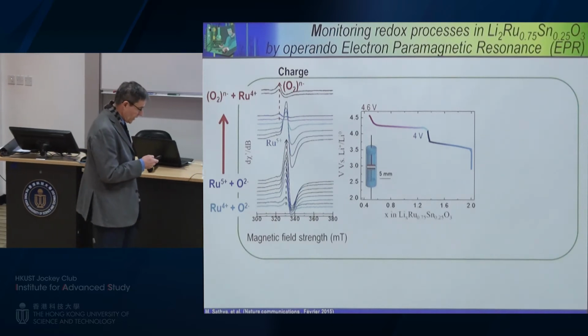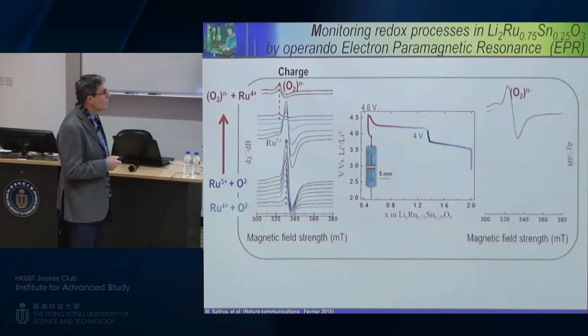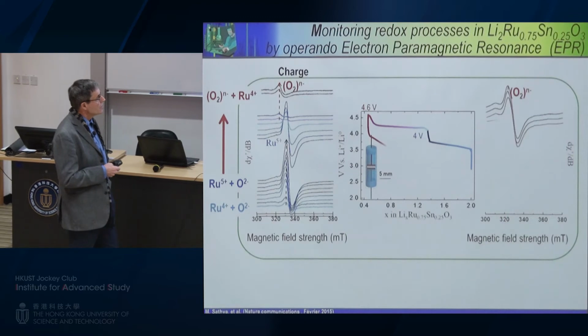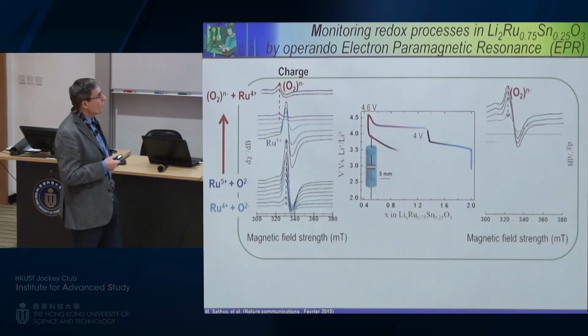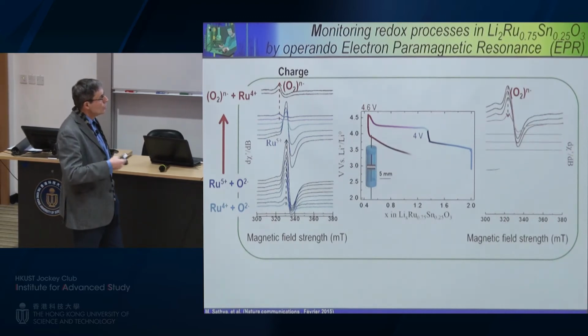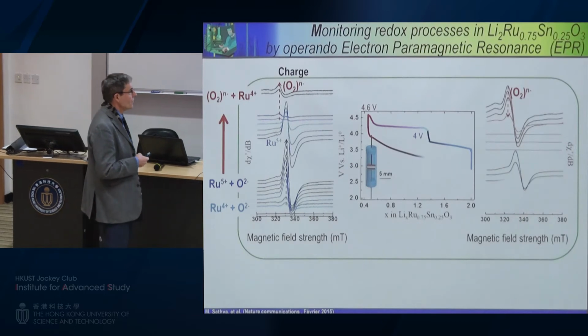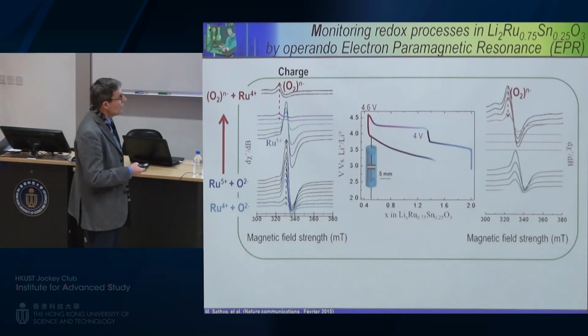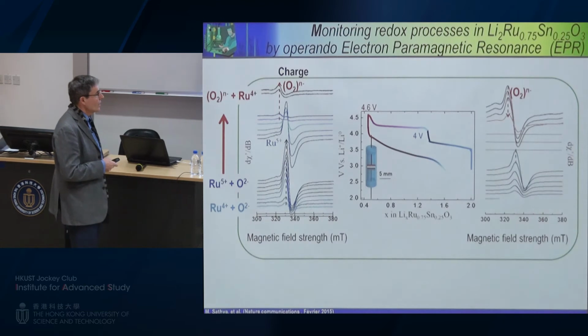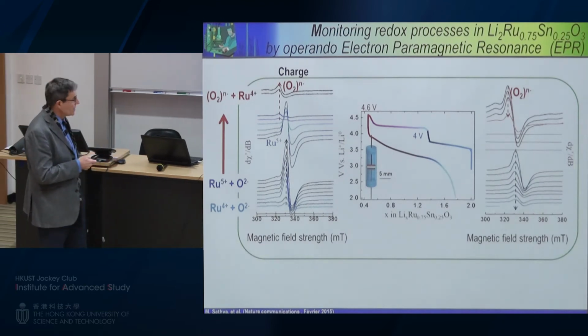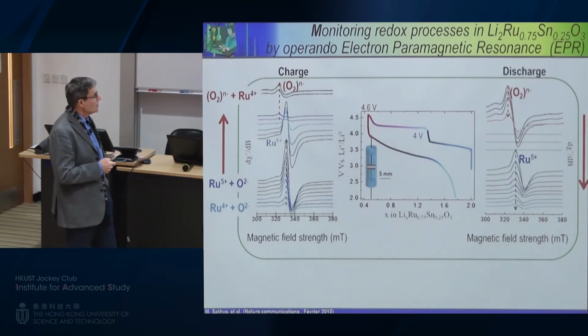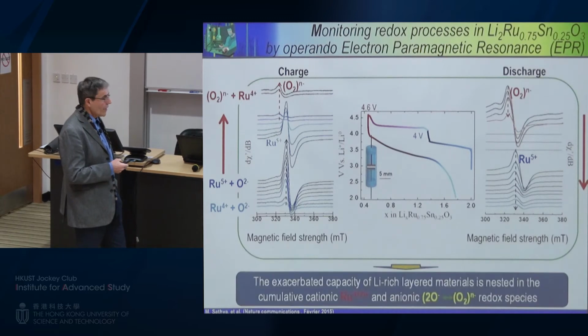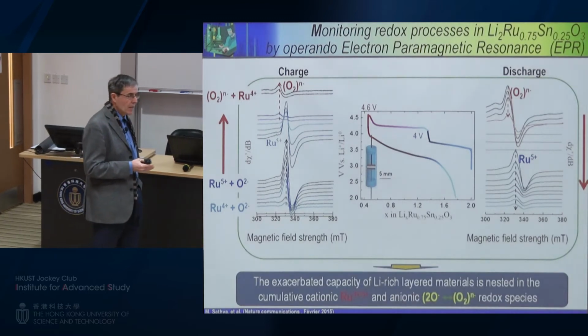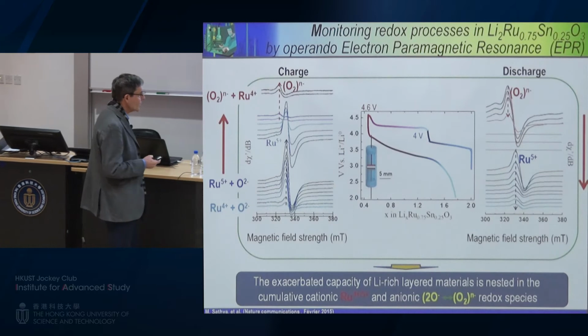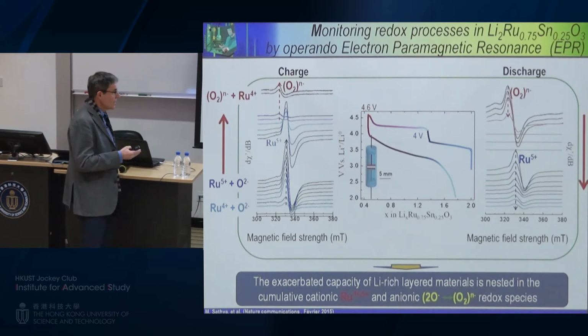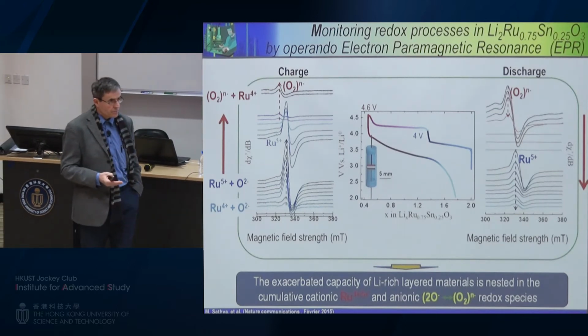And of course, the process is reversible. When you go down on the charge, the peak associated to the peroxo-like species disappears at the expense of the ruthenium plus 5 peak, which again disappears to come back to ruthenium plus 4 and the final material. And you can see here, we have clearly shown that the exacerbated capacity in this compound is due to the cumulative cationic and anionic redox species.